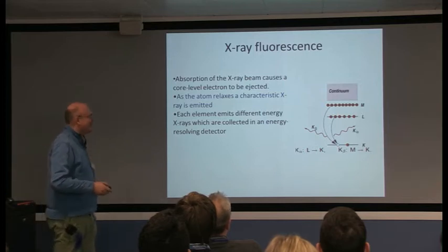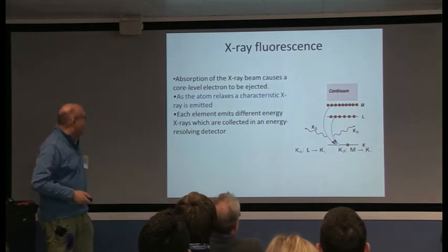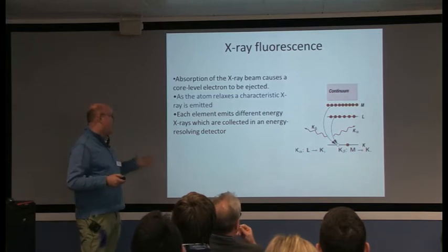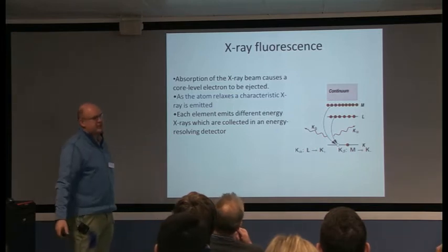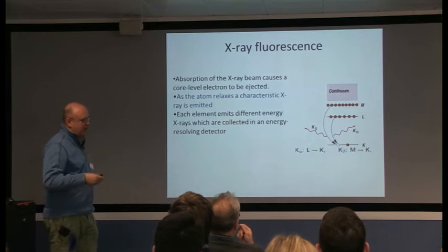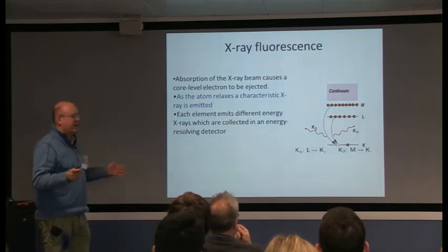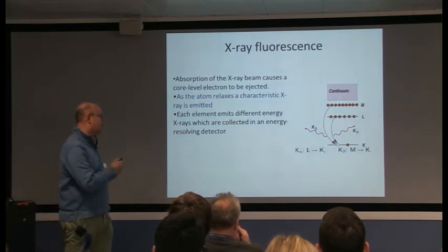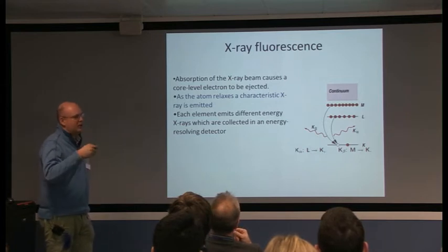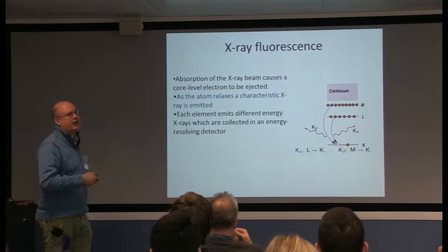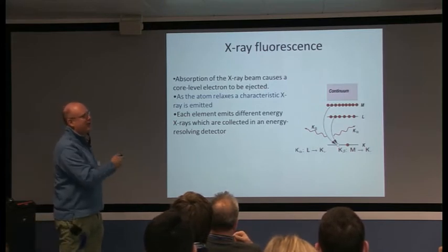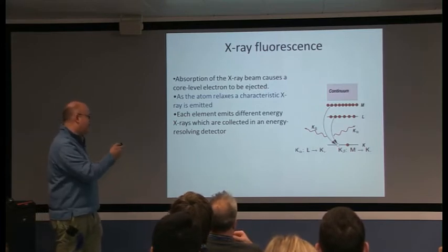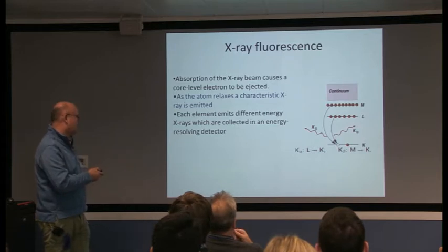Less well in the lower energy regime, where the fluorescence yield is considerably lower, but on I-18 they do have fluorescence available, and for some things, as I'll show in an example of arsenic, it's really useful because when you have lots of L lines, they can overlap with some of the K lines, and therefore fluorescence can really pick out the element better than transmission, and it can also go a lot more dilute.